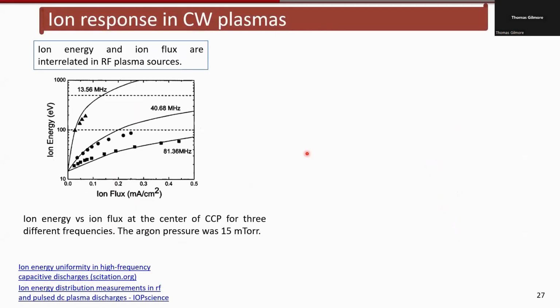If you go back to CW plasmas, here is ion flux versus ion energy at different frequencies, and you can see again, there is a relationship between the two, like they're both linked in tools. Here, increasing power increases the energy more. In this case, increasing power increases flux more. So using different frequencies helps, but it is not linear.